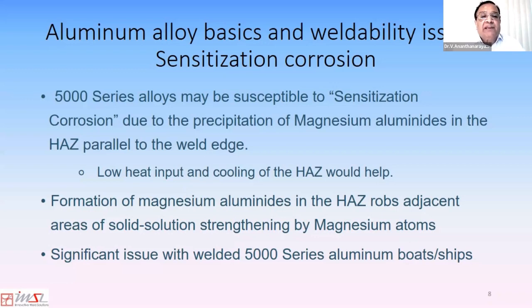Another problem with the formation of magnesium aluminides is that the adjacent regions lose magnesium that goes into the formation of these aluminides. And as you know, much of the strengthening of the 5000 series alloys is due to the solid solution strengthening by magnesium atoms. So when magnesium atoms are lost in the heat affected zone in the formation of magnesium aluminides, it's a double whammy. The area becomes sensitive to saltwater corrosion and it loses strength as well.